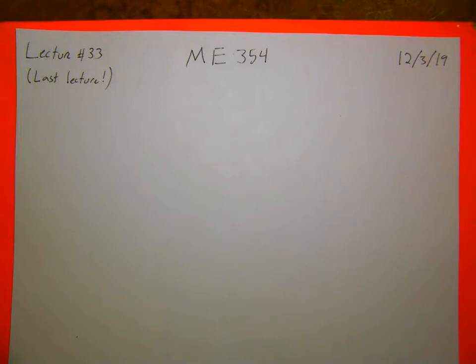One of the first things off the bat we noticed was that the strain to failure is very, very high, and that the modulus here is very low relative to what you would expect for a tensile specimen. I didn't realize it would be so far off, but if you remember for the tension lab way back when, we had given you clip gauges on the axial and transverse parts of the gauge section. There's a reason for that, and the reason is that these things slip in the grips.